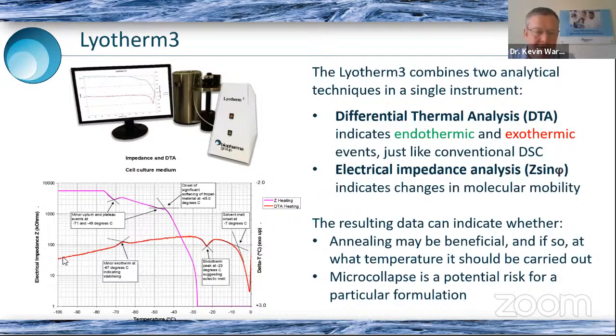And we combine that with differential thermal analysis. So the red line here is showing us, as we warm the solution from -100, a slight exotherm around -70. Well, that coincides very nicely with the change in the impedance. And that indicates that somewhere around -75, the frozen solution starts to become slightly more mobile, and that is just ahead of this crystallization. So they fit together very nicely.